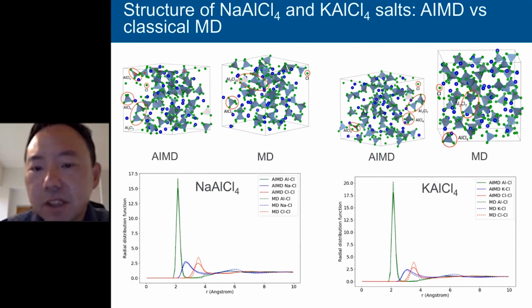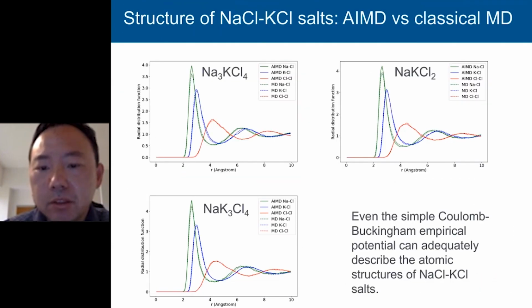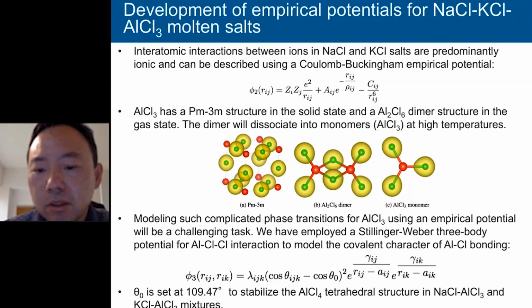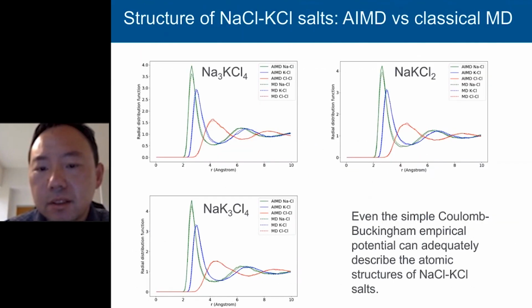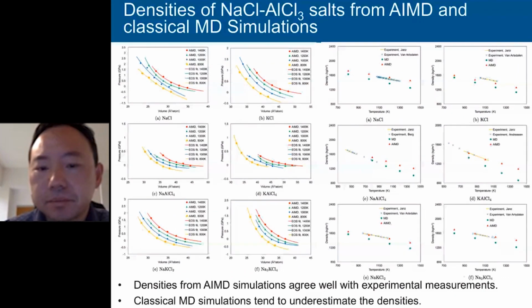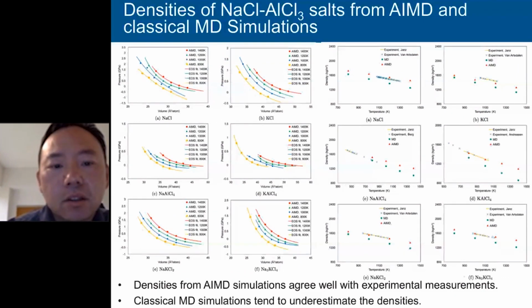And the same thing can be said for the mixture between potassium chloride and aluminum chloride. Again, the comparison between the Ab Initio MD and the classical MD is good, but not great. If you look here, there's some discrepancy between the chloride radial distribution functions, which I believe is due to the neglect of the aluminum chloride monomers in the molten state. So now let's go to the results.